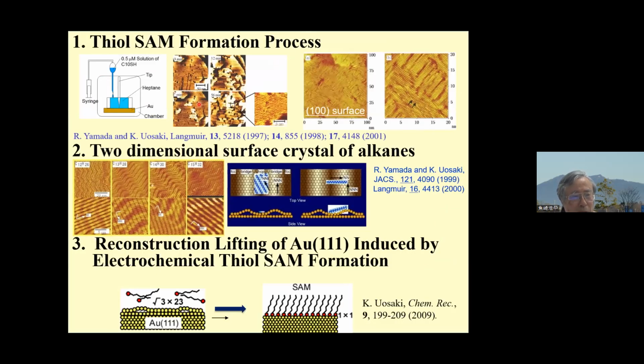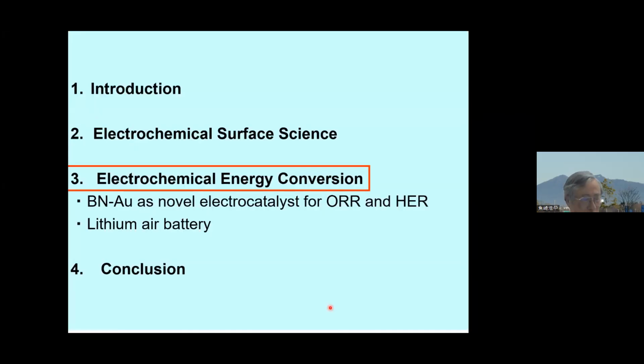So we see the thiol monolayer formation on top of gold 111, how it is atomically shifted, and the structure is different whether the substrate is 111 or 100. Even also we can see the individual molecules in the case of alkane, and also how, when the thiol molecule is adsorbed on the gold 111 surface, the first layer structure changes from the root 3 by 23 reconstructed structure to 1 by 1, by surface X-ray diffraction.